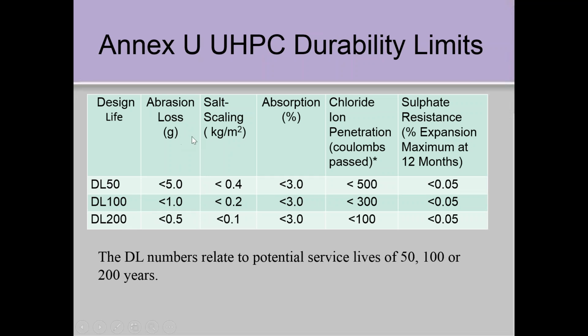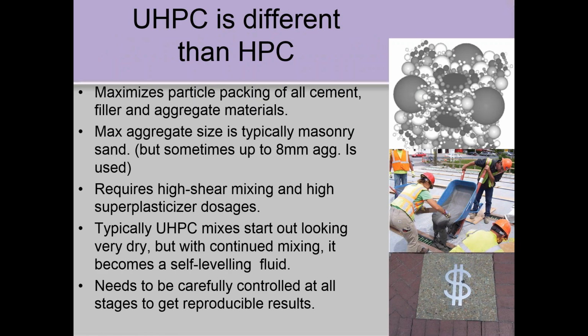Now they're a bit arbitrary, but they've set requirements for things like abrasion loss for pavements, or things like dam spillways, salt scaling requirements, which are much tighter than the MTO's requirements of 0.8 kilograms per square meter. Absorption requirements, chloride permeability requirements, the Coulomb values. You can see they're very low. And sulphate resistance. That's what's in there now. It's an annex. It's not mandatory, but it's an annex.